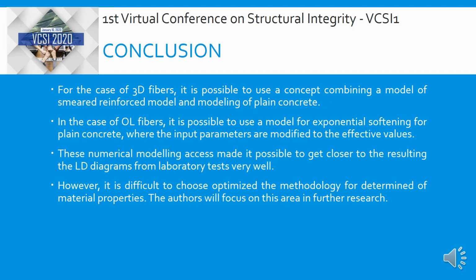For the case of hooked fibers, it is possible to use a concept combining a smeared reinforcement model and modeling of plain concrete. In the case of small fibers, it is possible to use a model with exponential softening for plain concrete, where the input parameters are modified to the effective values. This numerical modeling approach made it possible to get very close to the resulting LD diagrams from laboratory tests. However, it is difficult to choose an optimized methodology for determination of material properties. The authors will focus on this area in future research.